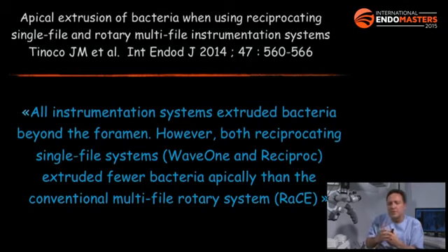In this case, remember that when you take the multi-file RaCe, every file is going to length. So, of course, you will use the Pre-RaCe in the coronal area, but then you will take the 15 to length, followed by the 20 to length, followed by the 25 to length. Then every single file going to length will push a little bit of debris. While when you use a file in the coronal area first and you irrigate, then you go deeper and you irrigate, and then you go deeper and you irrigate, the tendency of this file to extrude debris will be limited to the final millimeters of the canal, because you have enlarged the coronal part and cleaned all the coronal part before getting your file to length, which is not the case with the files that you get one after the other to length.